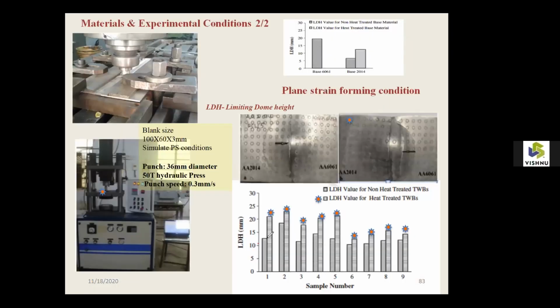So this is the one without heat treatment. That is 6061 and 2014 without heat treatment, it cracked here, because the elongation of this is 22% and the elongation of this is only 12%. So this elongates so nicely, but this one won't elongate at all. Because of that, it results in a crack. So this one is heat treated, that is, solution treated and aged. This is the virgin metal, that is, non-solution heat treated.